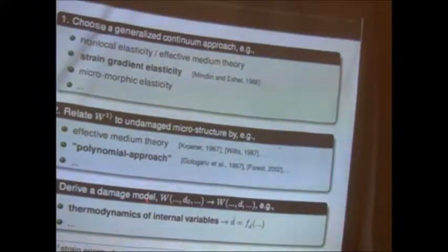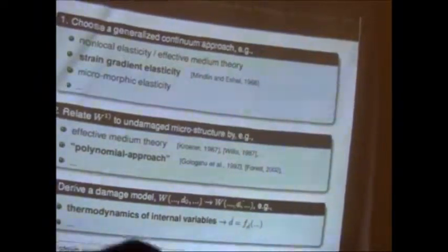Having this for the undamaged material, what we would like to do is develop a continuum damage model based on this strain energy density by, for instance, applying thermodynamics of internal variables to get an evolution of damage into the model.